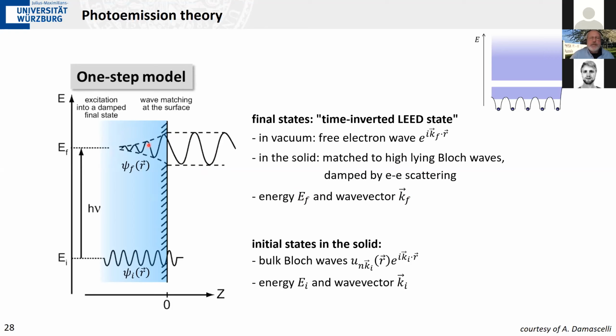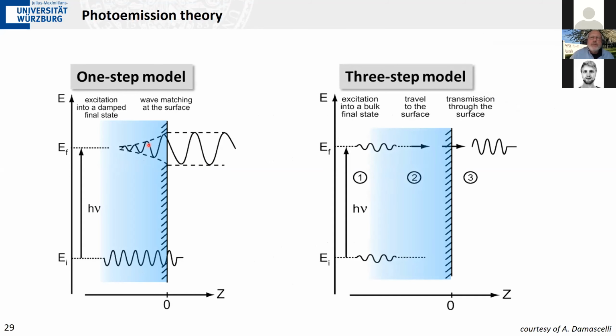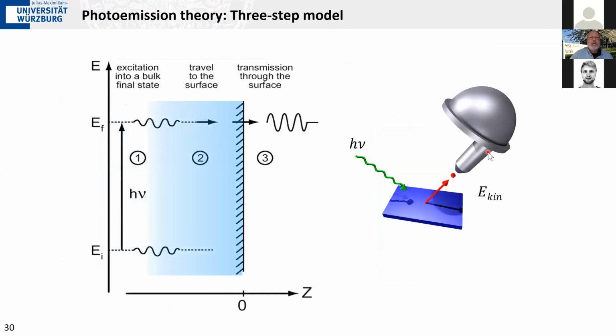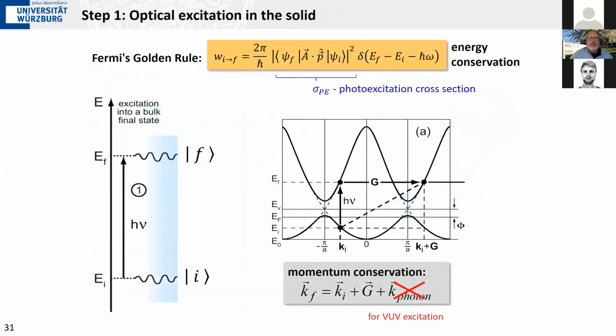but that's on a theoretical side not easily handled, and therefore what people have come up with is a simplified scheme in which you break this down into 3 independent steps. And that's called the 3-step model. You start out with an excitation deep in the volume between Bloch states, initial state Bloch state and the final state Bloch state. Then you treat the propagation of the photoelectron towards the surface, and then you take into account what happens at the transition from the volume, from the crystal into the vacuum. And that's what we will be looking at now. This 3-step model, and let's start with the first step.